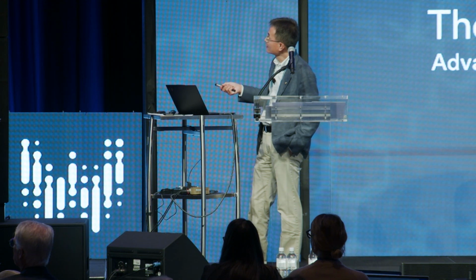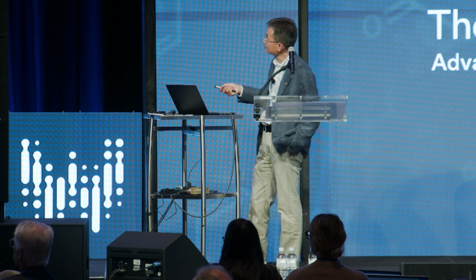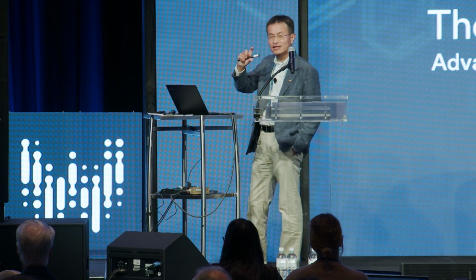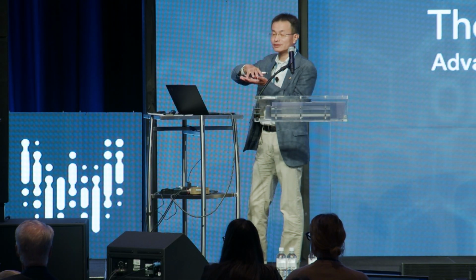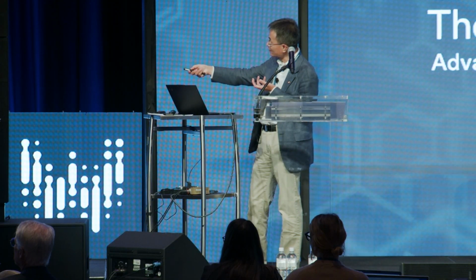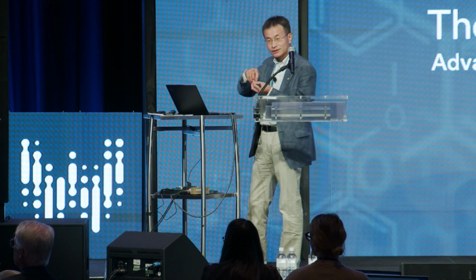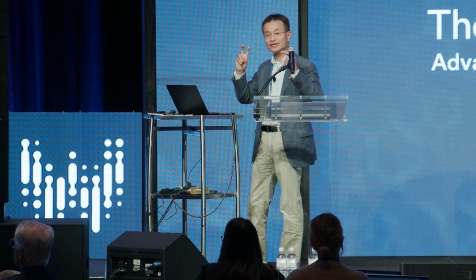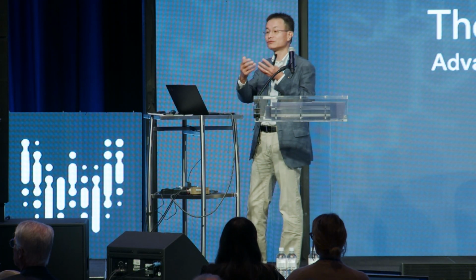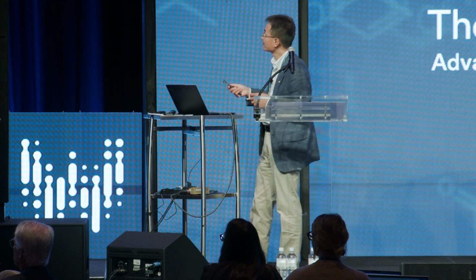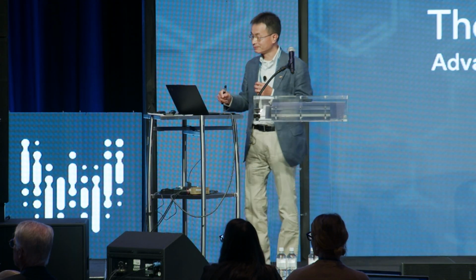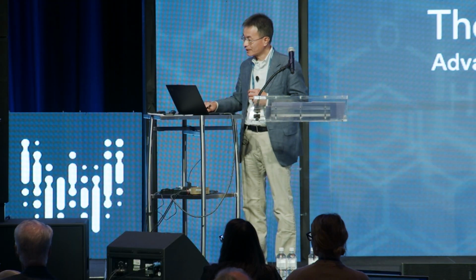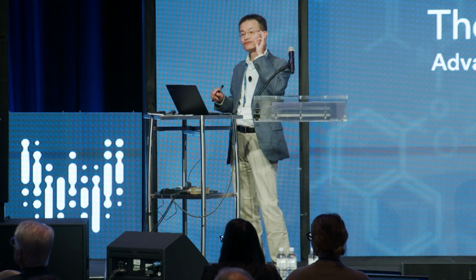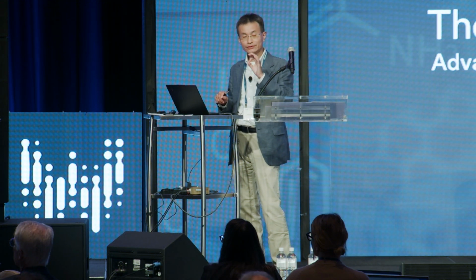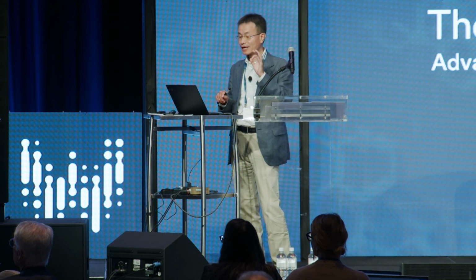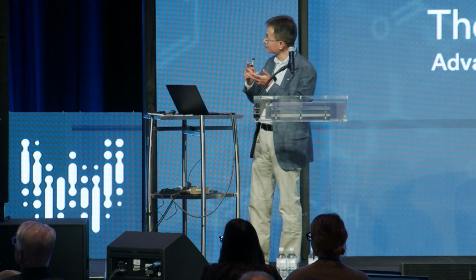You can see that these are some oxide nanowires, which back then we used for flux line pinning in high temperature superconductors. You use these linear nanoscopic objects to pin the flux line so that you can enhance the so-called critical current density, the current density you can carry without losing any energy. That's basically the first example from my Harvard PhD time. And that actually leads into the first example of using the VLS methodology to grow inorganic semiconductors like MgO and zinc oxide.